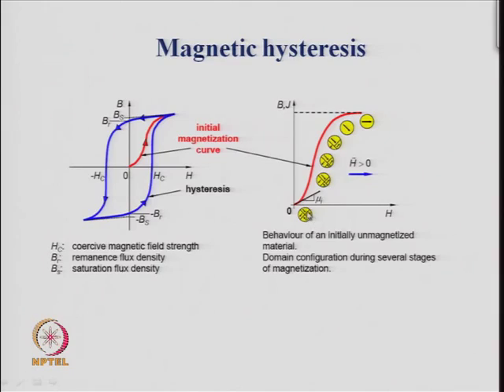Here there are 4 quadrants, all the 4 quadrants are equal, the vectors are pointing in different directions, the net magnetization is 0 or the net magnetic flux density is 0. When you are here, then you see some of the quadrants being higher in energy and hence you have a net magnetization or a net magnetic flux density, and that region grows in area, and so this region is increasing till you come here. You had 4 domains here, you had 4 domains here, here also you had 4 domains, but very small domains some of them and one large domain. Here now you have again only 3 domains and one large domain out of the 3. Finally, you have only one domain, only one vector you have.